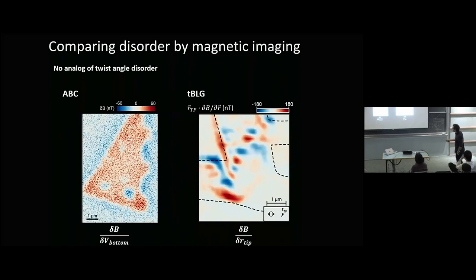But one of the things I want to point out, so I'm showing you here scanning probe magnetometry data using nanoSQUID on tip microscopy, comparing that same ABC sample with a ferromagnetic twisted bilayer graphene sample in the quantum anomalous Hall state. And I want to point out that this is a micron scale bar here. And you can see that basically the magnetism is essentially uniform over this whole flake. There's a couple of small bubbles. These are actually residue at interfaces that are introduced during the fabrication process. Because there's residue underneath one of the gates at this particular spot, you're not at the same density and displacement field as you are elsewhere. But basically, it's uniform. This is just the shape of the device.